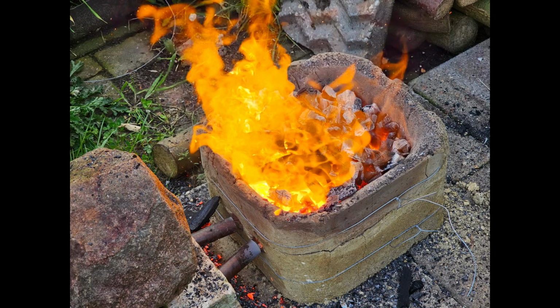It is even found that due to the high amounts of charcoal ash that are used during the hearth refinement technique, the slag inside of the steel will have an elevated calcium and potassium content, in particular with a ratio of about 2 to 1 calcium to potassium, or in a broad sense between 4 to 1 and 1 to 1, as is normal with hardwood ash like oak or beech.